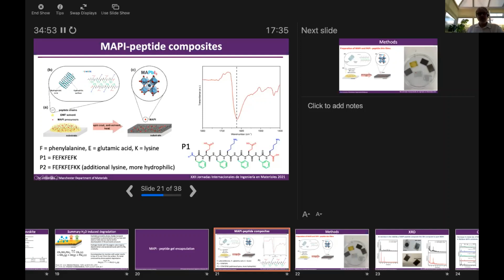So the first thing we wanted to do was to ensure that DMF would also form these beta sheets, so that when we saw this gel, we were getting a similar structure to what we'd see with water, and that's what this spectrum is. This is an FTIR spectrum of the peptide gel swollen with dimethyl formamide, which is the solvent we usually make MAPI precursors in. Normally, you would use a mixture of DMF and DMSO for your MAPI precursor delivery. But unfortunately, DMSO completely dissolves these peptide gels, so we've not been able to use that.